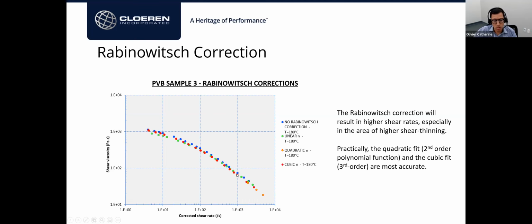Now, I didn't really comment between quadratic and cubic. In theory, cubic is better because you have a little more freedom to fit the data. However, if your data is a little noisy, it can amplify and create some error. So that's why you have to choose between the two. You've got to compare and see what makes sense. But most likely, I would never use the linear. Practically, that's what I found, right? But then I would spend maybe some time looking at quadratic versus cubic.